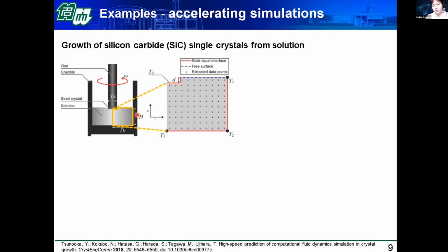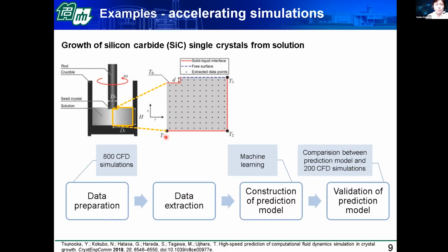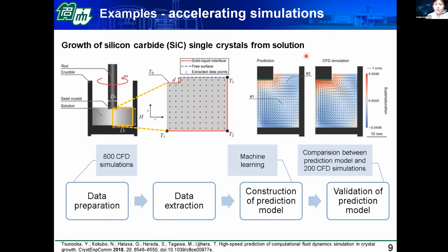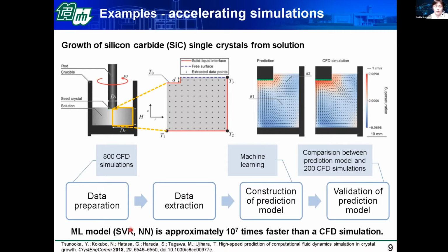So at first they had to gather the training data by running numerical simulations in this domain, which they did with 800, and then extracted data from those indicated points, which were then used to train machine learning models. And eventually the machine learning model was validated by another previously unseen 200 CFD simulations. If you compare the results of the CFD simulation and the prediction by machine learning, you can see the same general trends in terms of the fluid flow and the supersaturation field. And when evaluating this, it's also very important to notice the difference in speed. The machine learning models were several orders of magnitude faster than a CFD simulation.